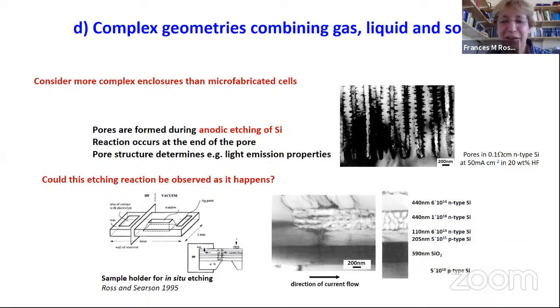And I want to show this one because it's very close to my heart. This was one of the things that got us interested in liquid cell microscopy. We were enchanted by the morphologies you can get when you do anodic etching of silicon. You get these channels, you get side branches, you get these dendritic structures, and the details of the structure determine the properties of the material. So how can we look at anodic etching in situ? Well, we could design a sample where silicon is only etched in a certain region because of the doping, and then we can use that silicon integrated object as the sample.